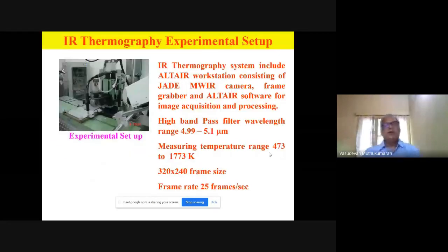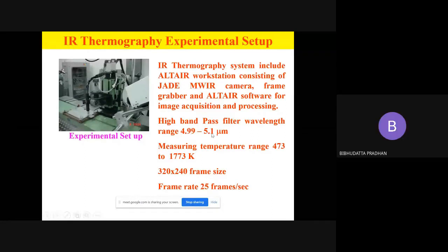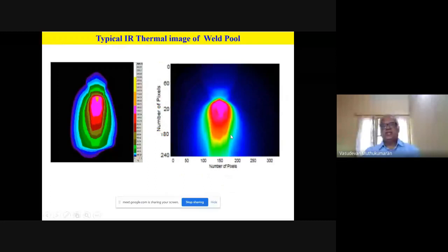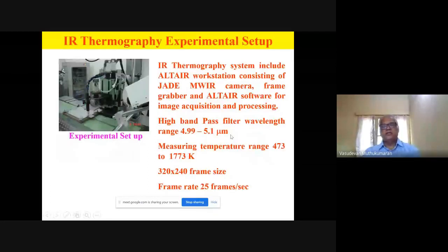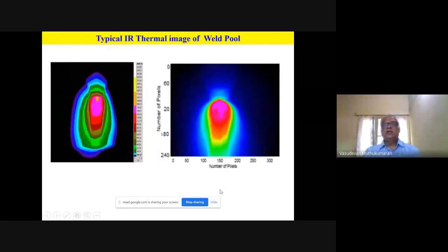You can see here we have integrated the IR camera with the TIG welding system so that in real time it could capture the weld pool images. These are the specifications of the camera: high band pass filter camera with wave range 4.9 to 5.1 micron, measurable temperature range 473 to 1773 Kelvin, frame size 320 by 240, frame rate 25 frames per second. You could see these are the typical thermal images we captured. This is after image processing, the typical weld pool image, the temperature isotherms.